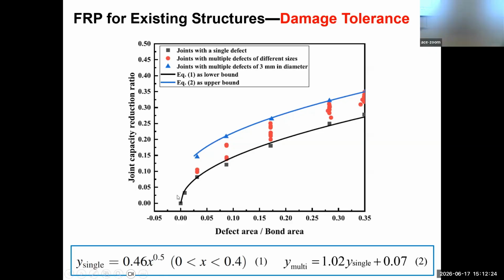The lower boundary here is the reduction factor for a single defect, and the upper boundary is the reduction factor for multiple defects. The data points in between these two boundaries are results from mixing different defects of different sizes and shapes. That means you don't need to care about the shape of the defect or the mixture of different sizes and shapes. You only need to work out the upper boundary - that's the maximum reduction of the bond line when you have a defect.